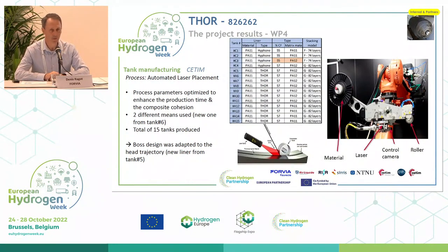We have manufactured 15 tanks with 2 different means and also 2 different liners, because in the first step we saw that the boss was an issue for the head to be close enough in the dome, so we have to modify the boss so that the head can be closer for the dome.